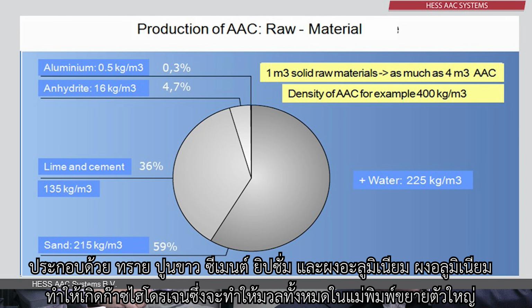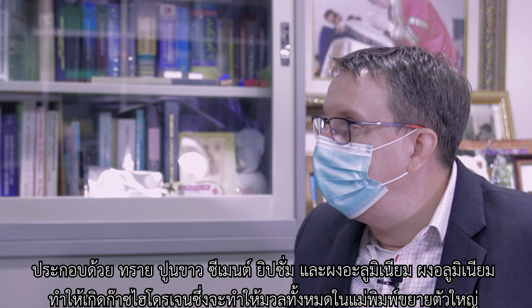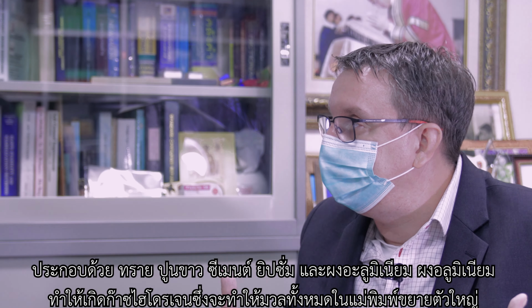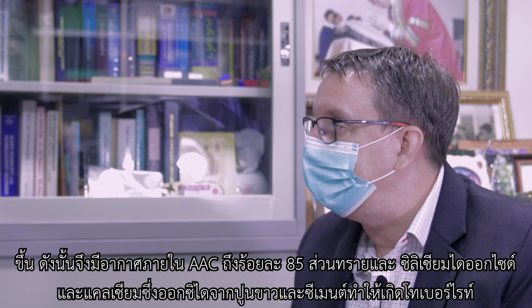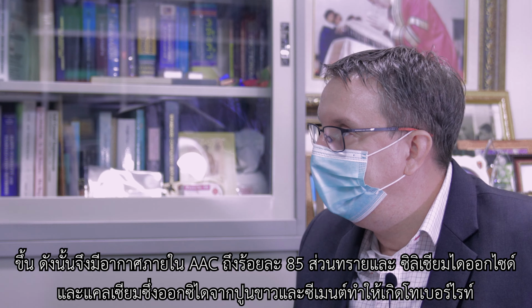If you manufacture AAC, you have several ingredients, raw materials which you mix together. So it's sand, it's lime, cement, gypsum, and aluminium powder or paste. The aluminium powder will create a hydrogen gas, which will let the whole cake in the mold rise and get bigger. So you have 85% of air inside the AAC.